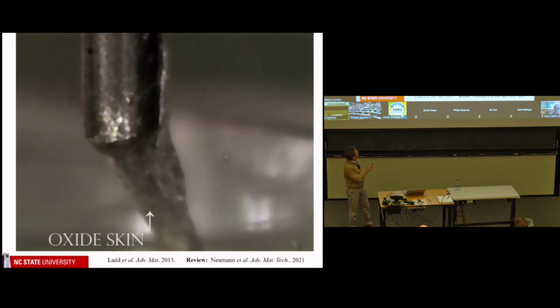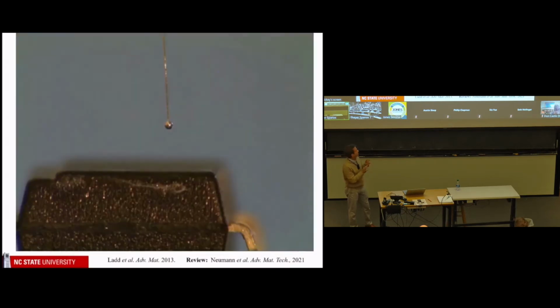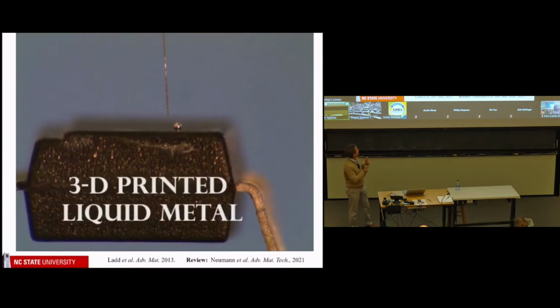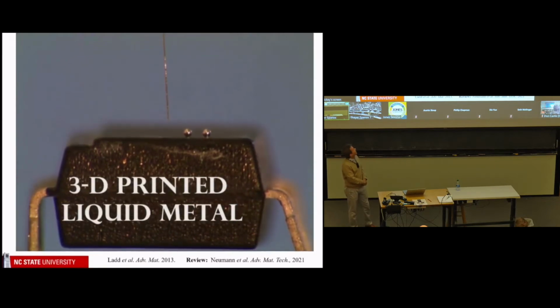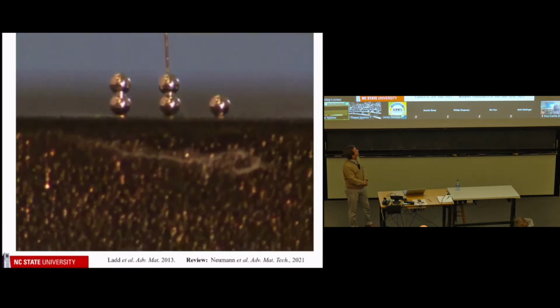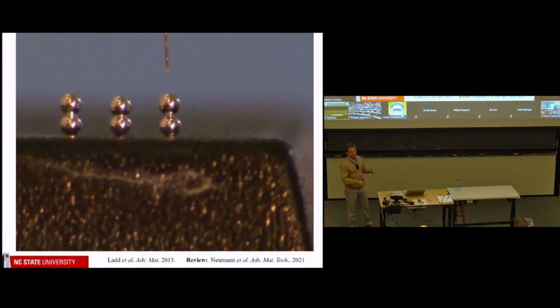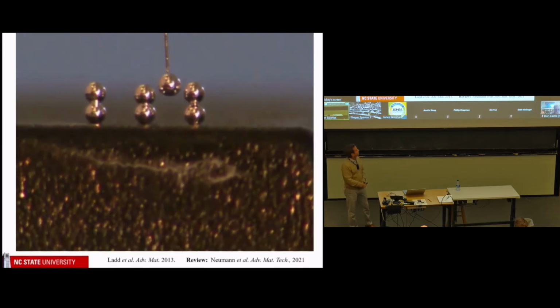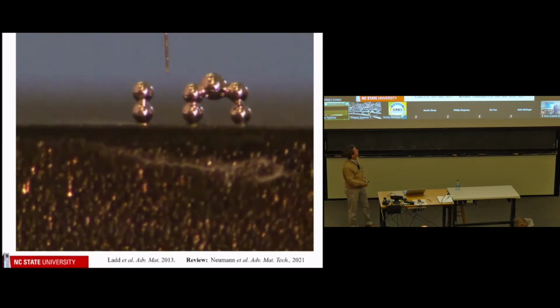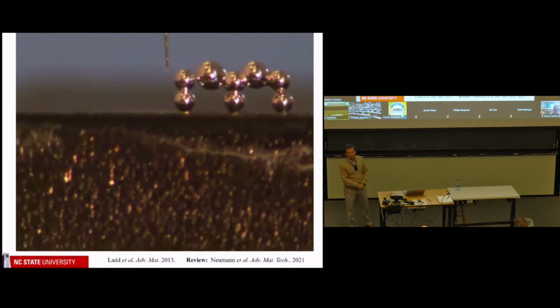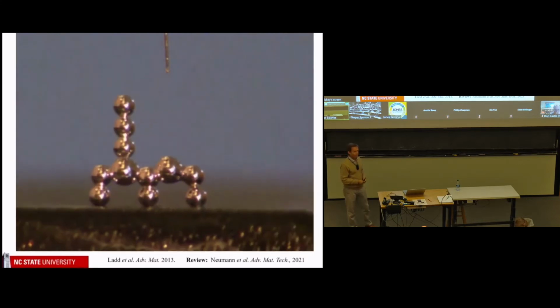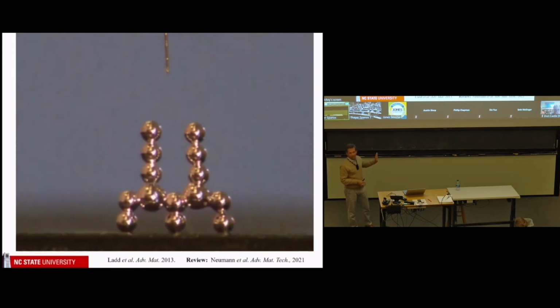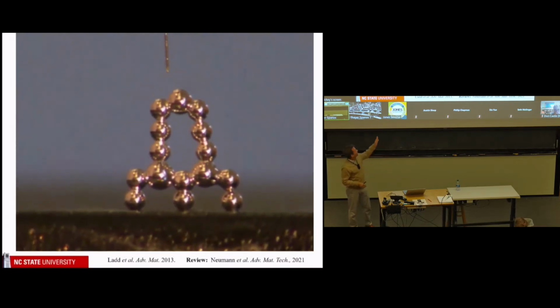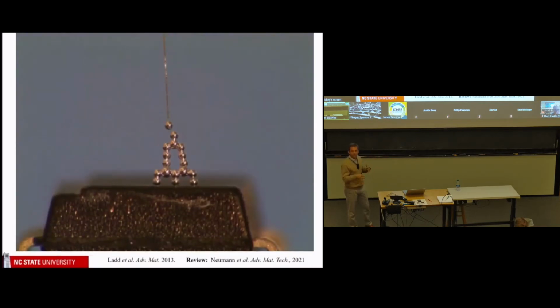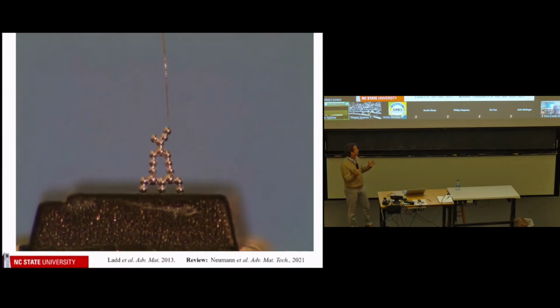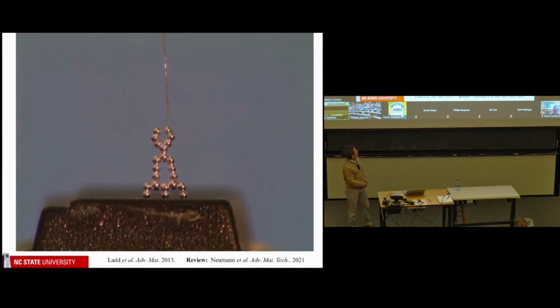So here, if we suck the liquid back into this nozzle, you see the oxide skin. Remember, it's only about 3 nanometers thick. You see it wrinkle. And this layer forms so fast and is sufficiently strong, you can start, for example, stacking droplets. And so this was kind of interesting work because it allows you, for the first time, to 3D print metals at room temperature. Now, not in any way that's structural. Truth be told, if you hit the table that this is on, it would fall over.